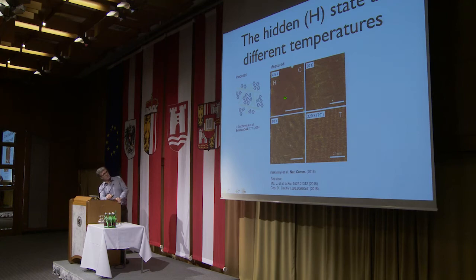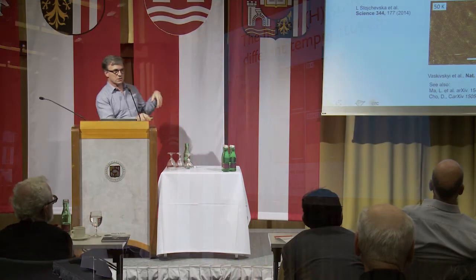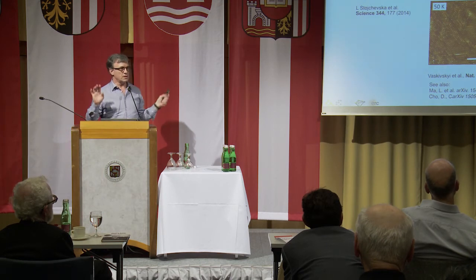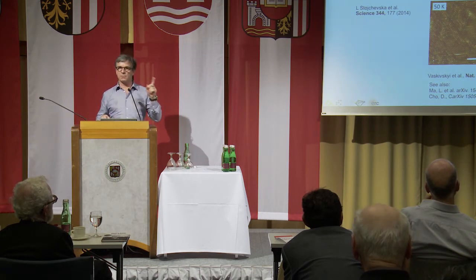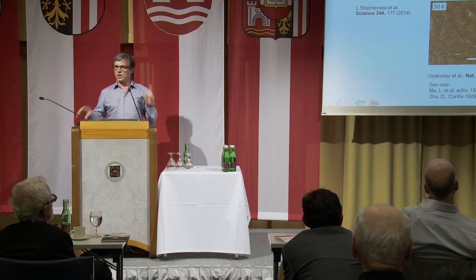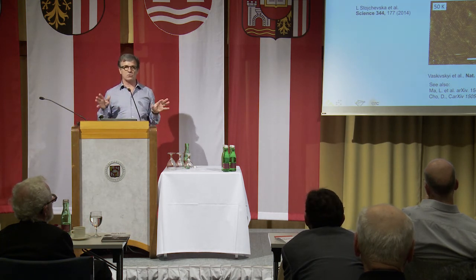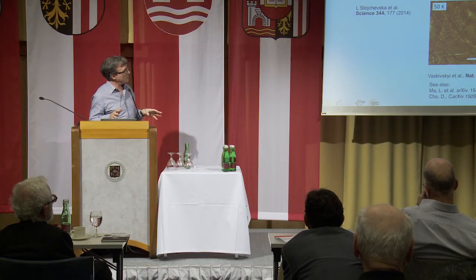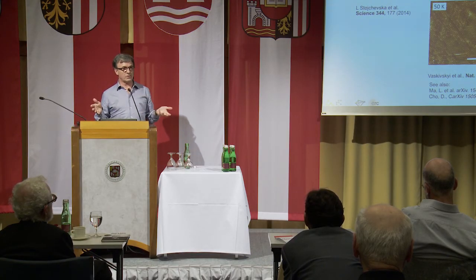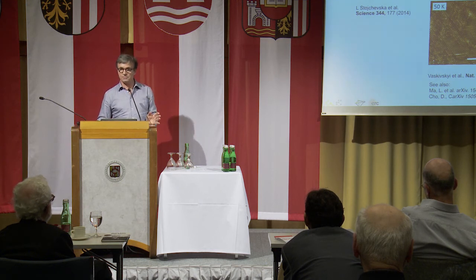That you actually see that at different temperatures, right? Eventually, it melts at 200 Kelvin or so. This order melts, and that's it. So basically, with a single laser pulse, 30 femtoseconds, we're changing the material. We have a metal insulator transition. The resistivity changes by a factor of 1,000, and we have essentially an ordered polaronic crystal.